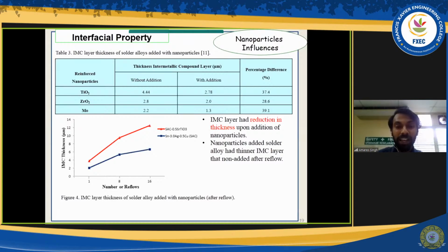Interfacial properties is actually the part between the solder and the substrate, between the solder and the printed circuit board. This is sort of like a layer that holds the component and also the printed circuit board. So we need a thin layer because a thin layer will preserve a good bonding. But when you have a thick layer, the thick layer is prone to crack.